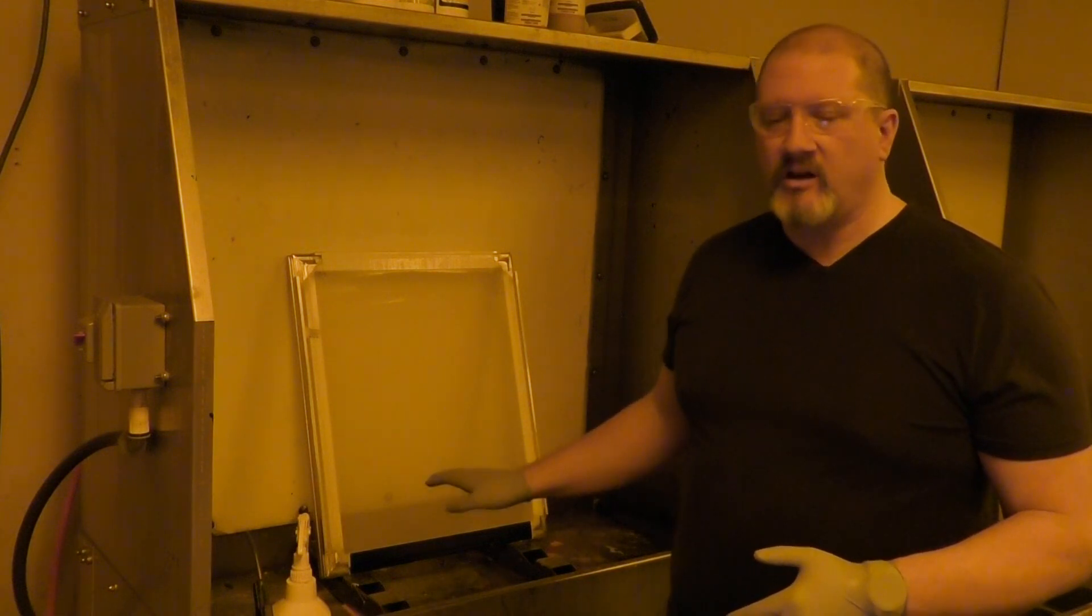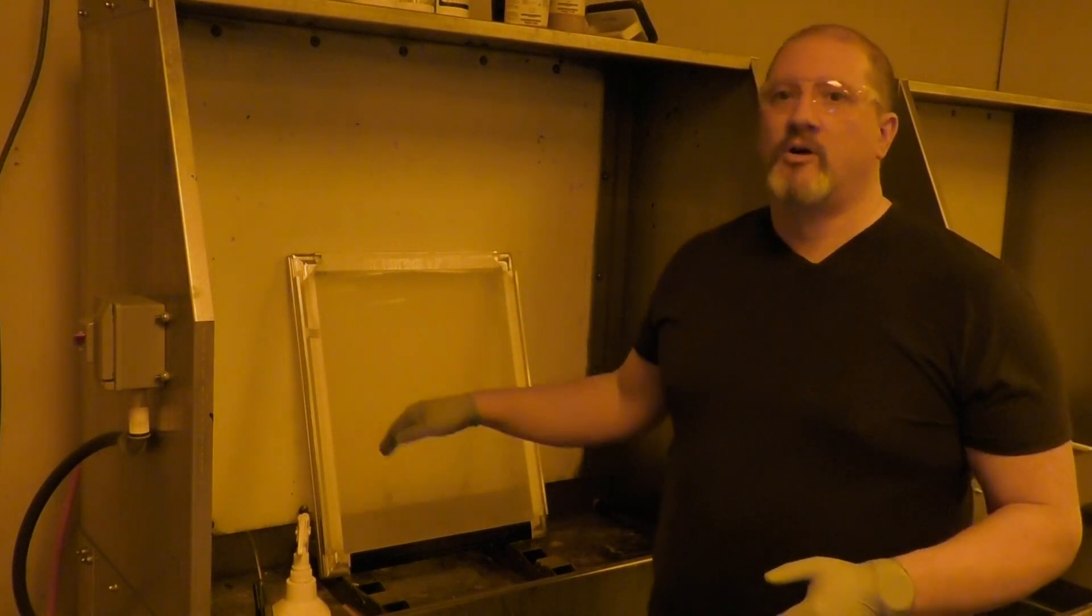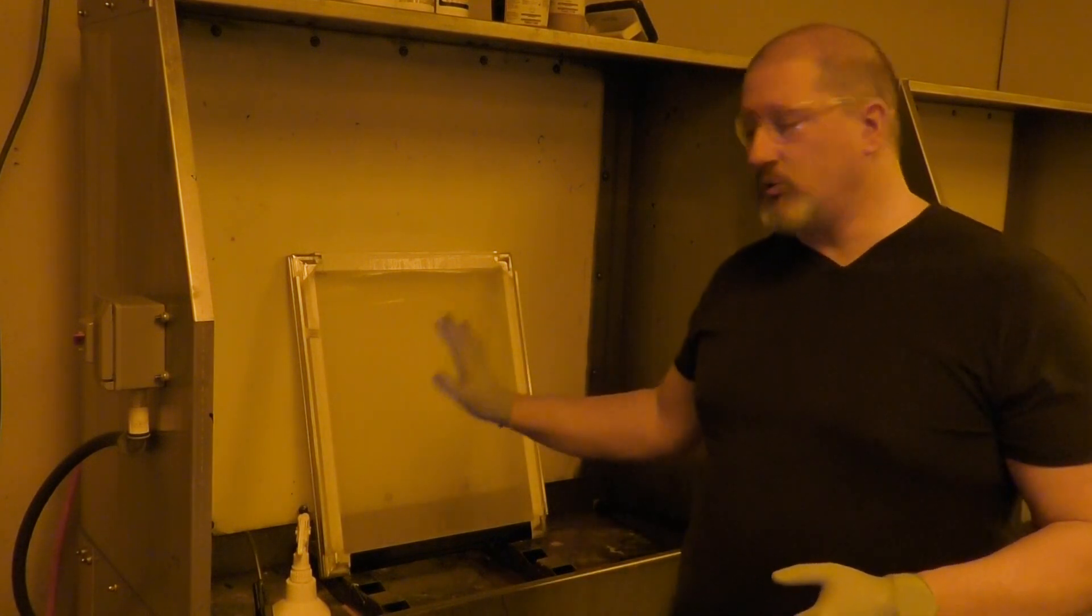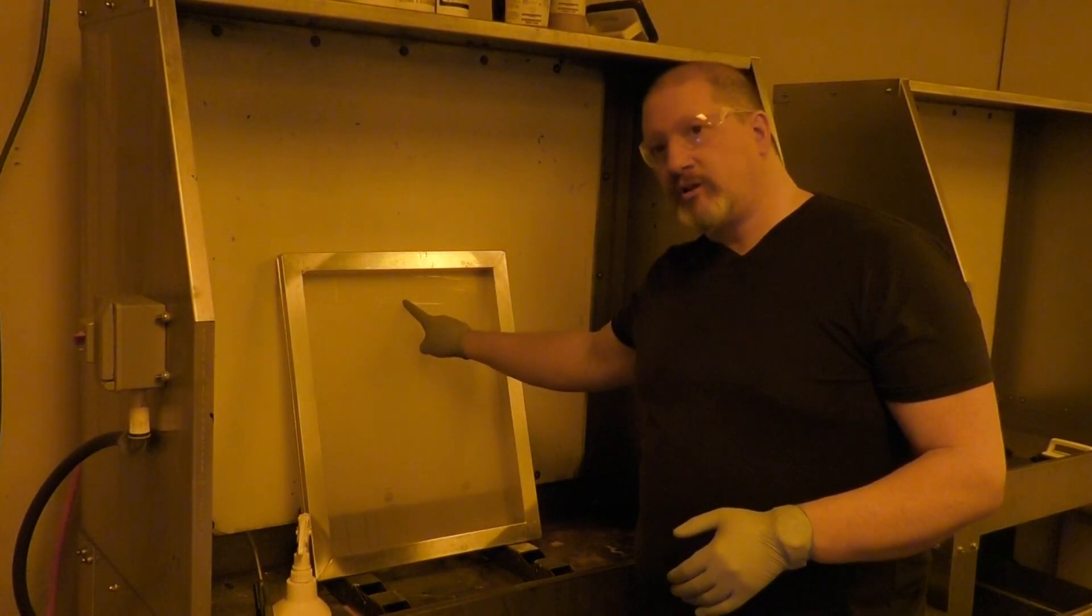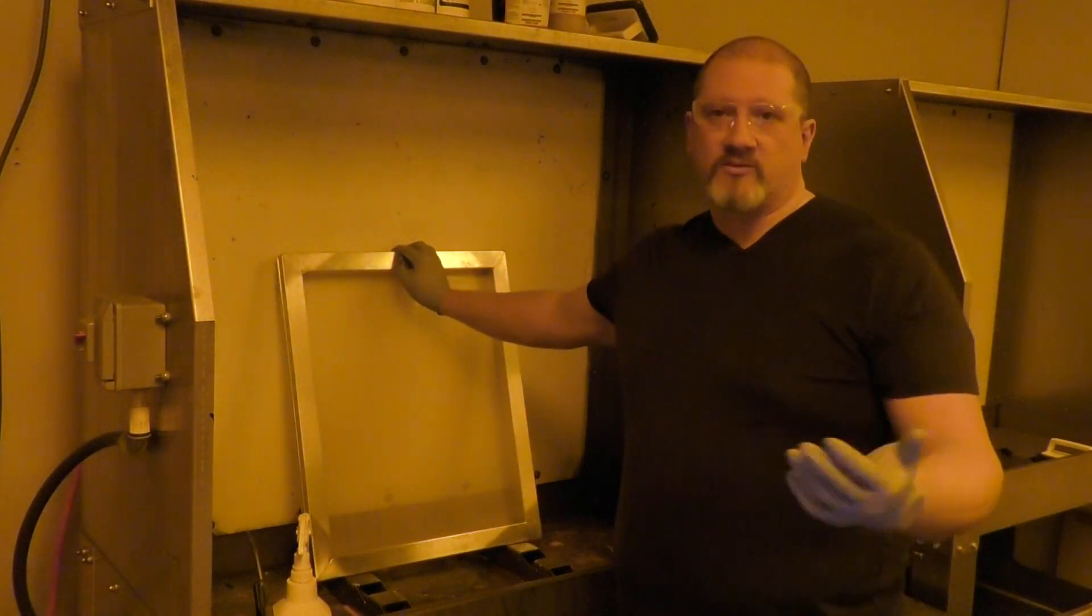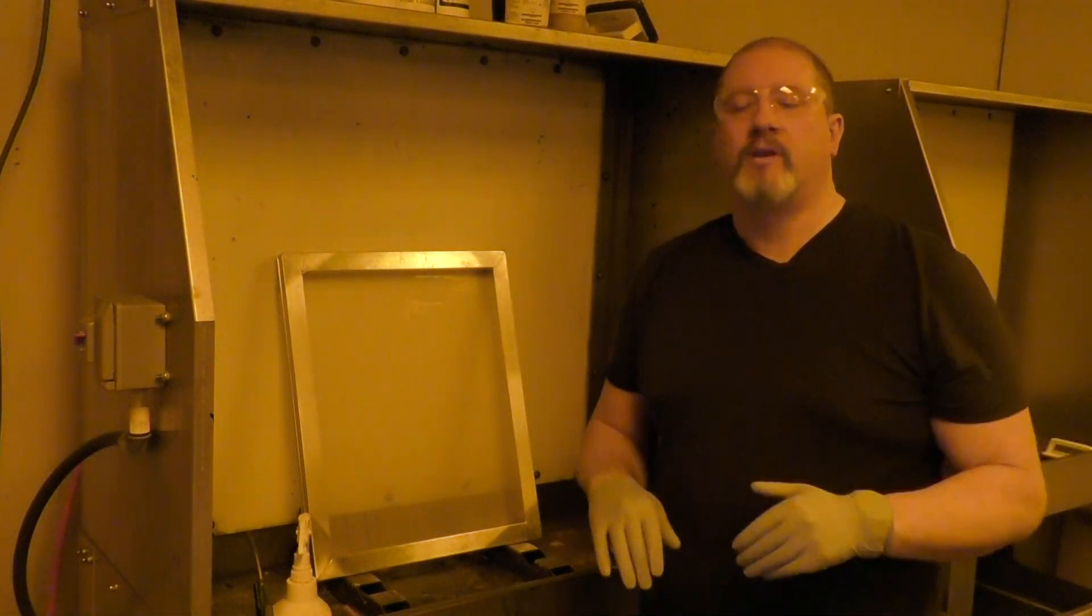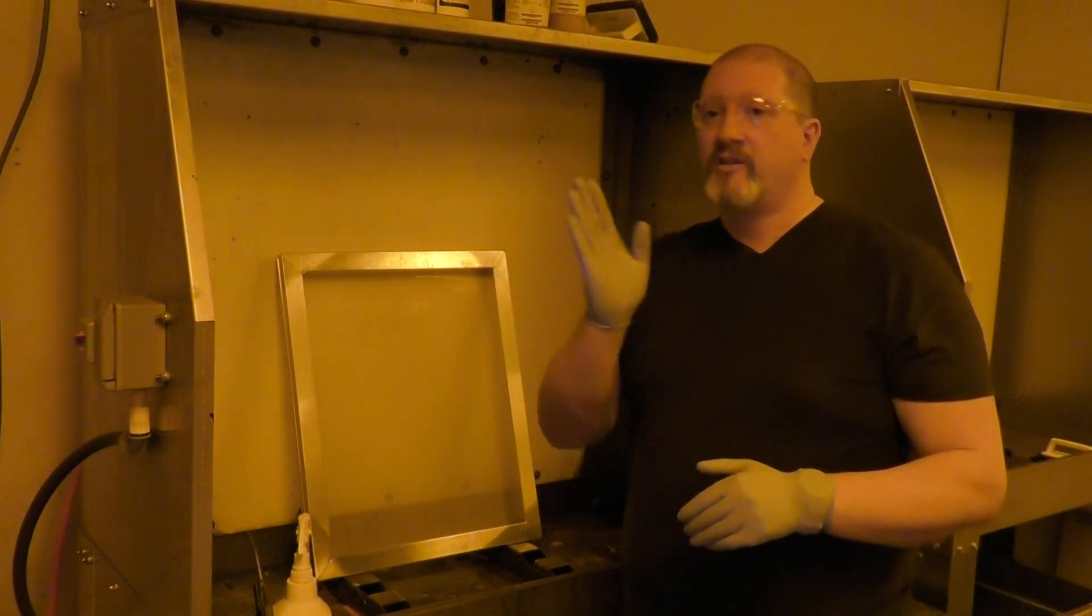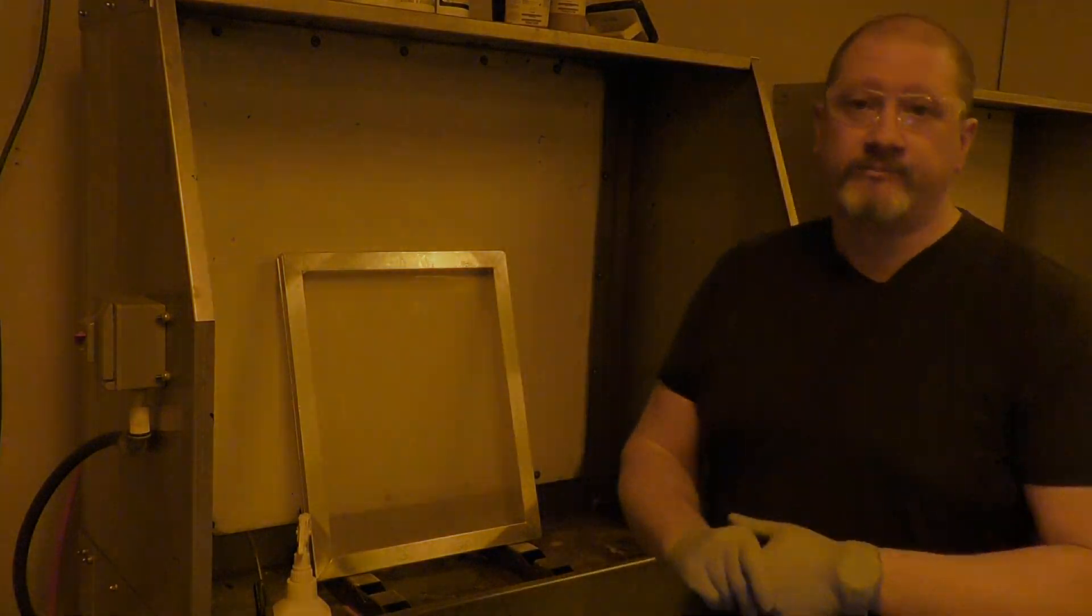One of the steps that you can use if your emulsion is locked in from using a solvent is you can use a haze remover on it. The haze remover specifically softens the emulsion so that a pressure washer can come back and blast it out. In those situations we recommend turning the screen around because your emulsion layer on the squeegee side is thinner than it is on the t-shirt side. That's because when we dry our screens from coating them with emulsion we let that emulsion form on the bottom, creates our nice stencil, our nice gasket. So we can actually blast it off from this side because the emulsion wrapping around the knuckles, the mesh itself is thinner there so we can blast it out.